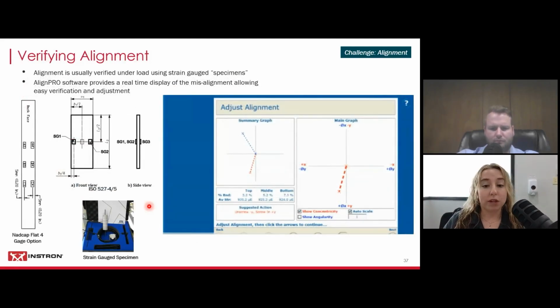So when we do alignment, typically what you do is you take an extremely stiff specimen with strain gauges, reading the top, middle, and bottom bending moments of your specimen. You load up your frame, and then you can read what the actual bending moment is occurring within the specimen itself. So there, Stefan is showing a top, middle, and bottom bending moment. And as the field service engineer, or somebody accredited within alignment, is adjusting the Align Pro, we're seeing the change in that bending moment actively happening.